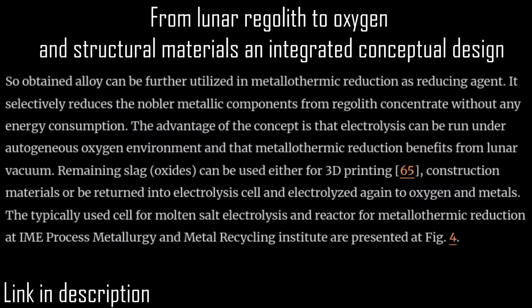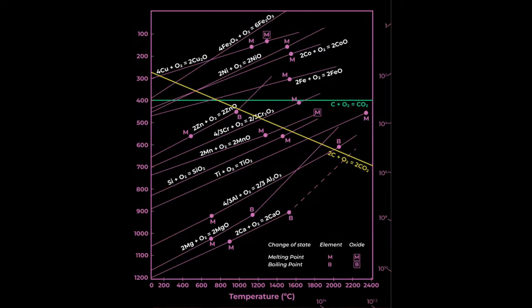And this is what that paper is proposing, in saying we would use our resulting alloy cake to reduce the next batch of regolith before it goes back in for electrolysis. This would create some pure iron, which could then be removed with a magnet once the mixture is cooled, or heat it more and wait for the iron to sink to the bottom, and you'd then re-electrolyze the remaining oxides and then redo the process. If this works, then it would be a fairly cheap way to produce pure iron with maybe trace amounts of nickel and chromium. But what about our other elements?